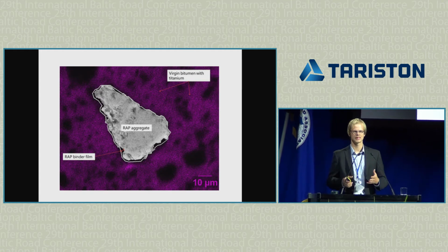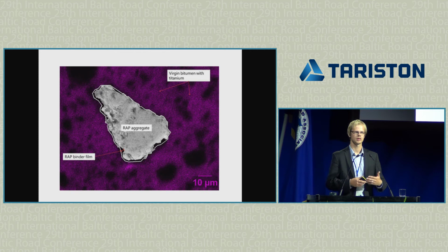And the result will, in most cases, be blending or binder activation somewhere between 0 and 100%. We probably will not be able to activate 100% of the old reclaimed asphalt binder. This is an image we took in another project. We replaced a portion of the filler with a tracer, titanium oxide. And you can see that the tracer is everywhere except on a very thin binder film around the RAP aggregate. This means that basically we are not reaching this binder. Although it's there in the mix design calculation, we would consider it as binder. Actually, it's more likely a part of the rock instead of being part of the binder.